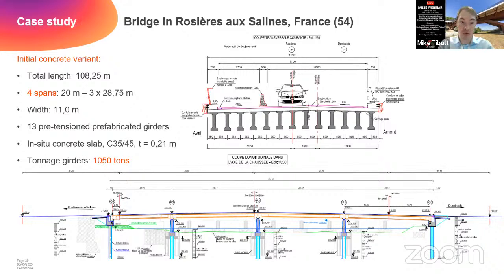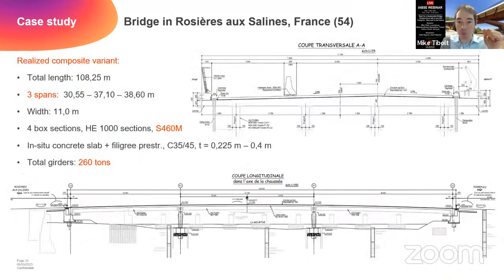The bridge has a total length of 108.25 meters, and it was foreseen in 4 spans between 20 and 28 meters roundabout. The slab was an in situ concrete slab C35/45 with a thickness of 21 centimeters. And the total tonnage of the girders, only of the girders, was 1050 tons. And as we also offer technical assistance in the design phase, so in the pre-design phase, we also worked out the solution using a composite solution between hot rolled sections and a concrete slab. And this was finally the solution that was retained for the construction.